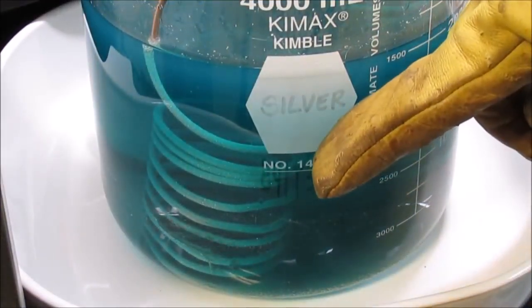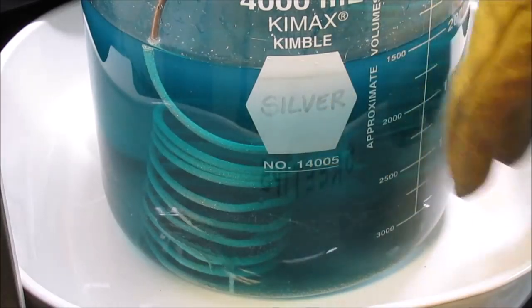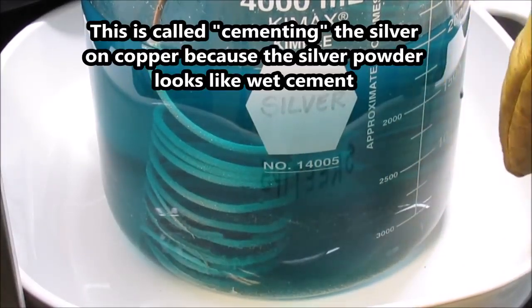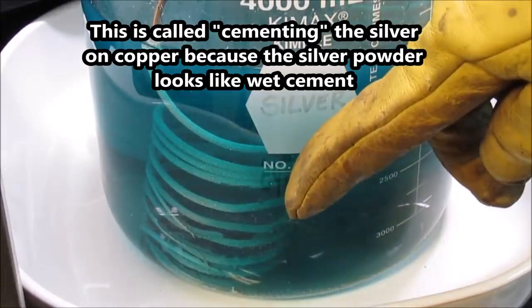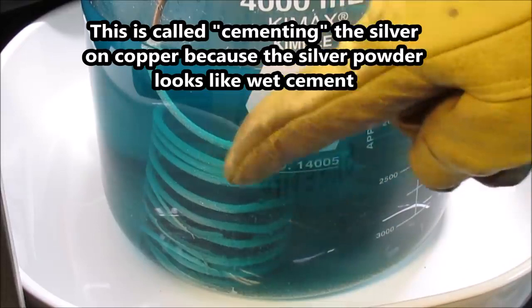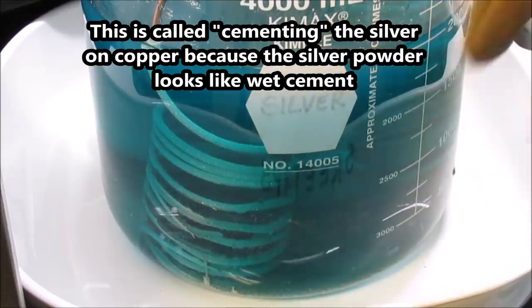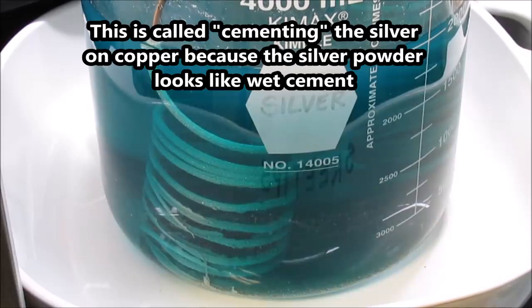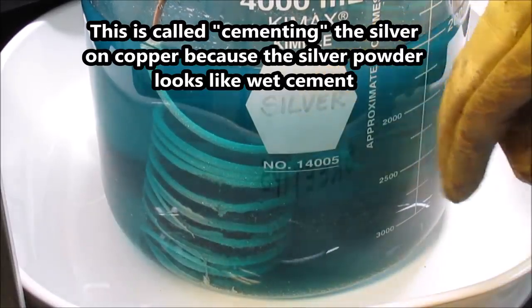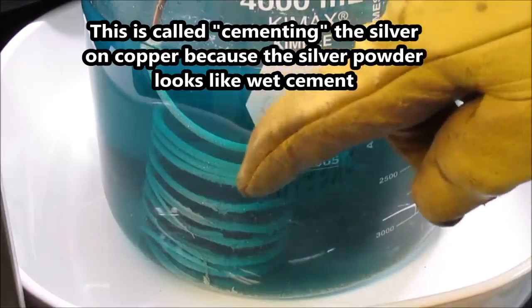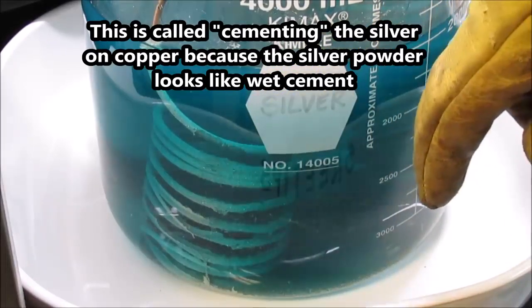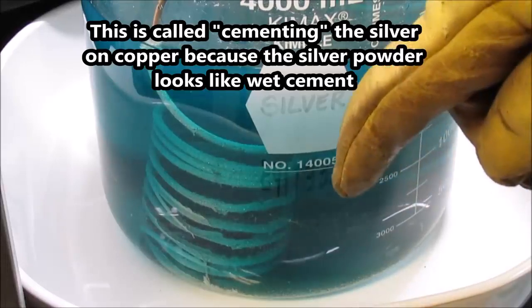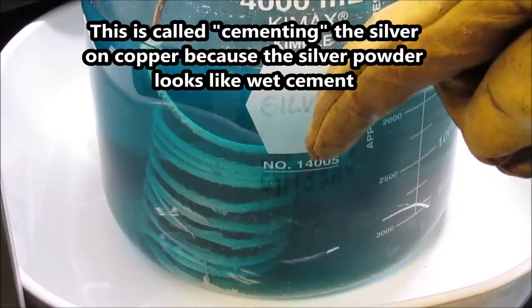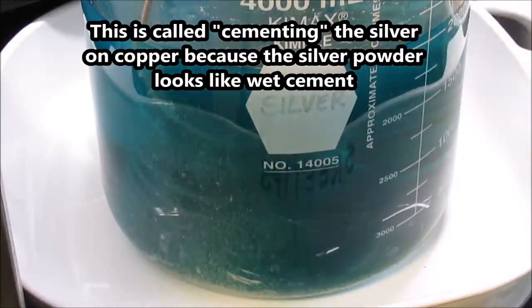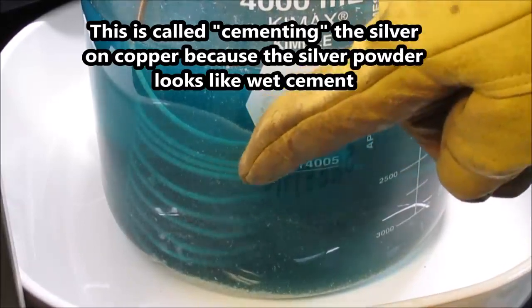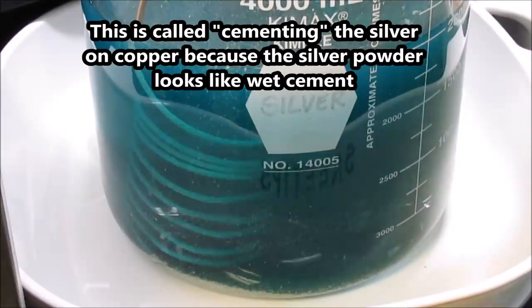Okay, what's happening here is the silver that's in solution is coming out of solution on the pieces of copper wire. That's pure silver powder forming on the copper, and as it gets heavy, it just drops off. While the silver is coming out of solution onto the copper, the copper is dissolving and going into solution. The two metals are trading places. The copper's going into solution, and the silver is coming out of solution. That's pure silver metal coming out of there.